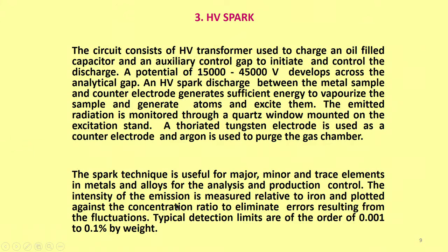So, we just put a small sample of iron which is pre-measured and then compare the signal, see that the iron sample matches with what you have put in, which means that all other elements also would be relatively free from interferences, or the results would be more accurate. As long as iron analysis is accurate, we assume that other samples' results are also accurate. So, this is known as an internal standard analysis.